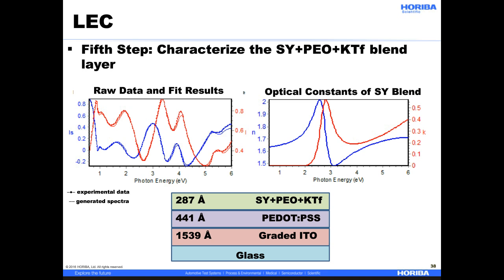Below that is the model. So this is super yellow plus PEO plus KTF on PEDOT-PSS, Graded ITO on glass. And on the right, you'll see the optical constants of the super yellow blend. Notice when we blend super yellow and PEO KTF, it's no longer a transparent material.